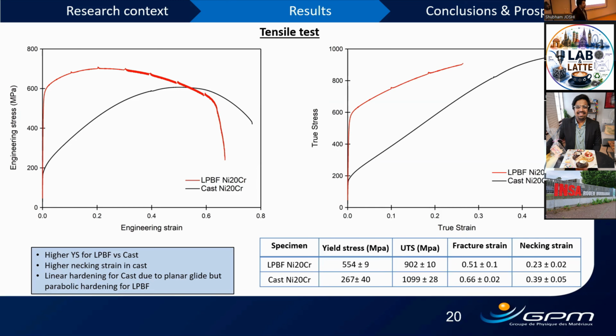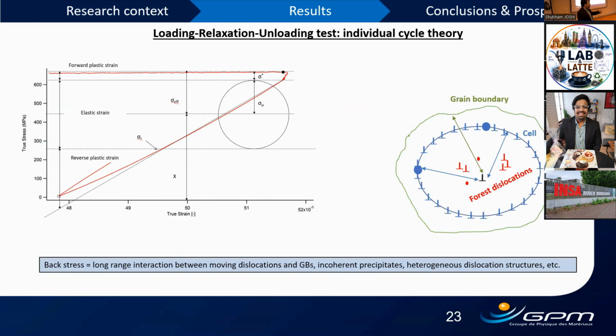So the explanation, or at least what we have extracted from this, is that whenever the beta parameter is huge, 10 to the power 12, or sometimes the values are minus 5 point something times 10 to the 12 or 9, it means that this feature is not responsible. If you see the formula, it's almost infinity. So the influence is 0. The model is based on fitting beta parameters depending upon how the two differential equations can be fit. So as soon as it gets the value that the whole feature is 0, it gets random values.